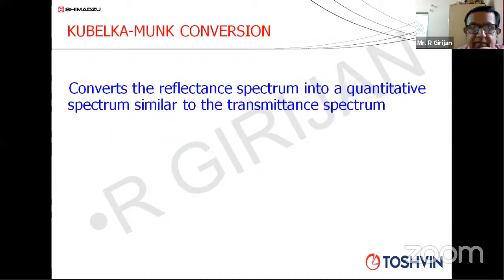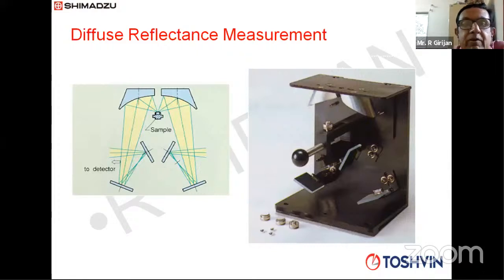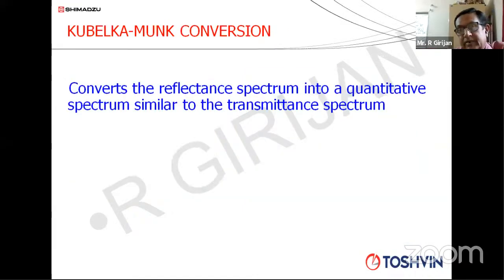There are small sample cups available. You can see some small sample cups, and hardly 3 or 4 milligrams will go inside a sample cup. The sample cup can be kept in the diffuse reflectance attachment, which you see on the right-hand side, and the sample cups are also shown below. This will sit in the sample compartment, and then you can record the diffuse reflectance spectrum of the material. That is what is called DRIFT analysis. Once you record a diffuse reflectance spectrum, you need to convert it to a normal transmission spectrum by a mathematical conversion known as the Kubelka-Munk conversion. It is to be applied in the software.